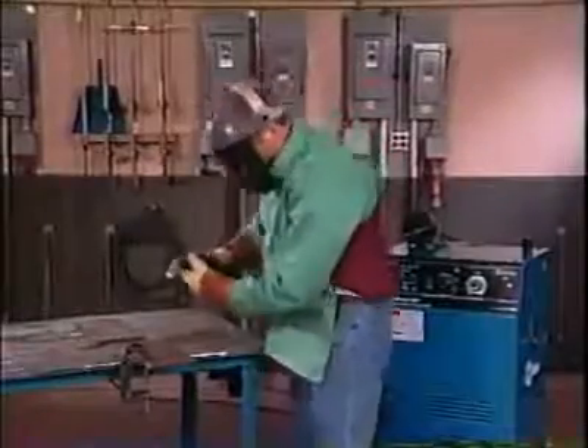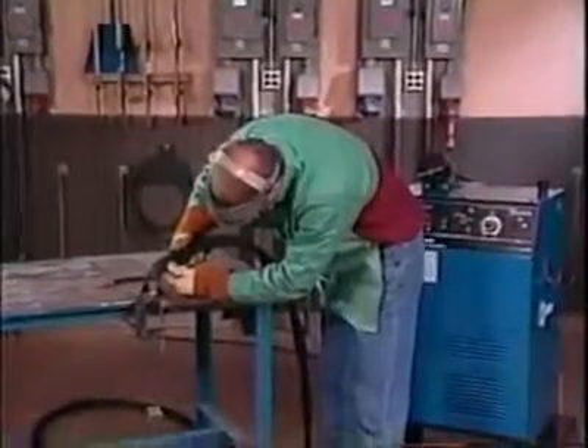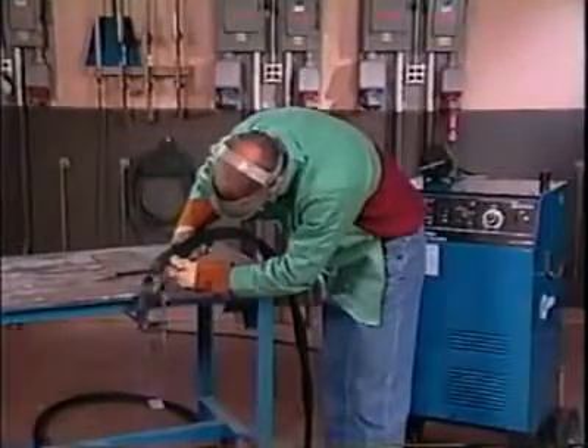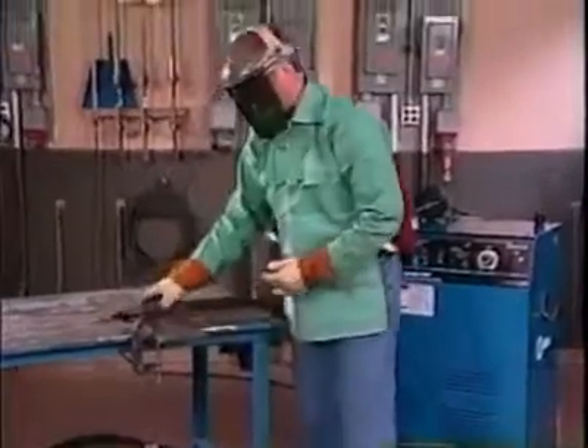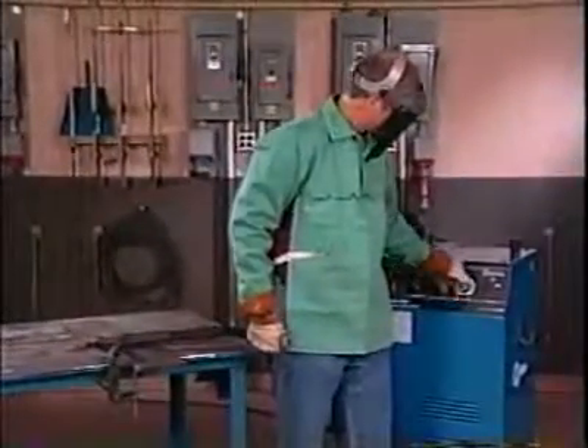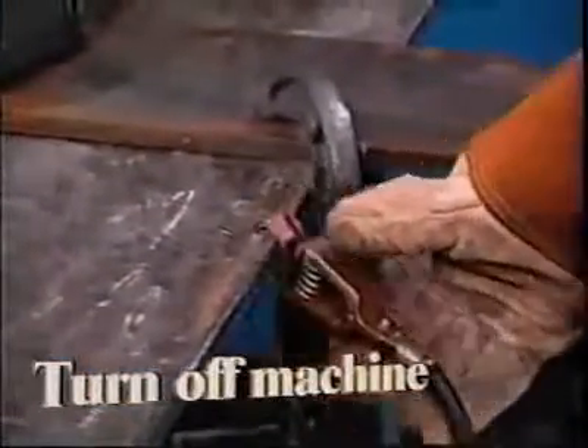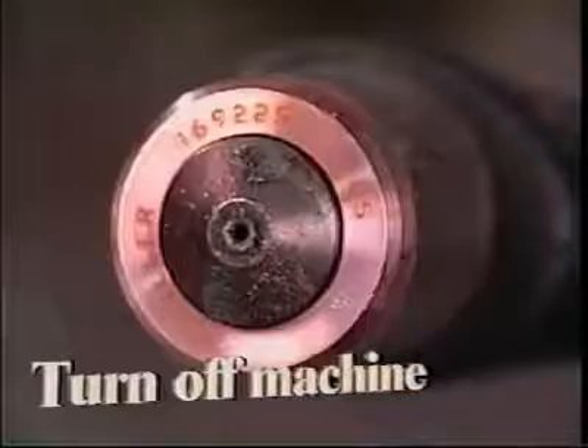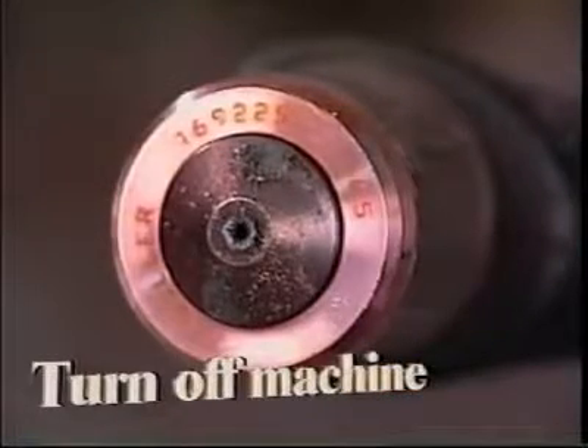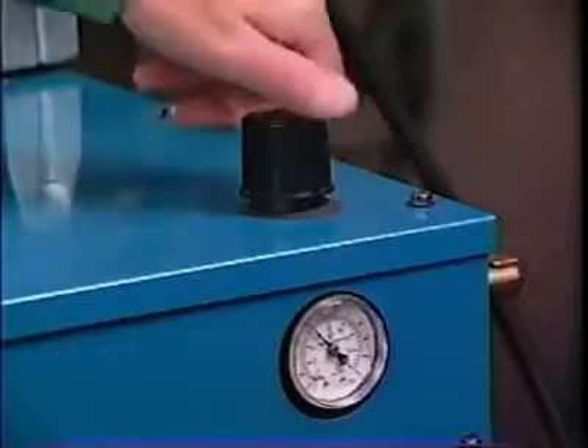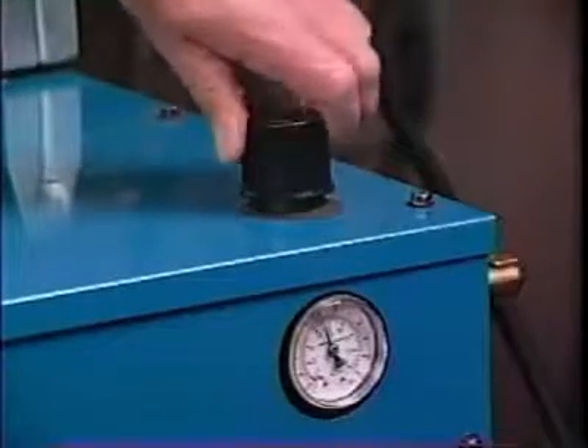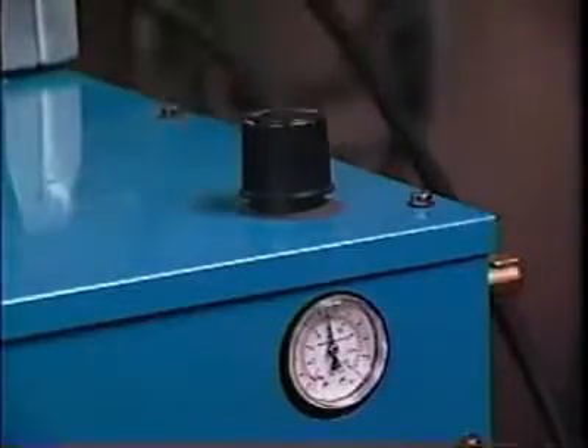If the arc does not penetrate the metal or the travel speed is exceptionally slow, extinguish the arc by releasing the trigger. Then, make the necessary amperage adjustments and start again. Attempt to correct the problem by assuring that the workpiece clamp is secure and close to the cut, assuring that consumables are not worn and are installed correctly, adjusting air pressure, and/or adjusting the power source amperage. If your cutting speed is too fast, molten metal will splash back upward and possibly short-circuit the tip and electrode.